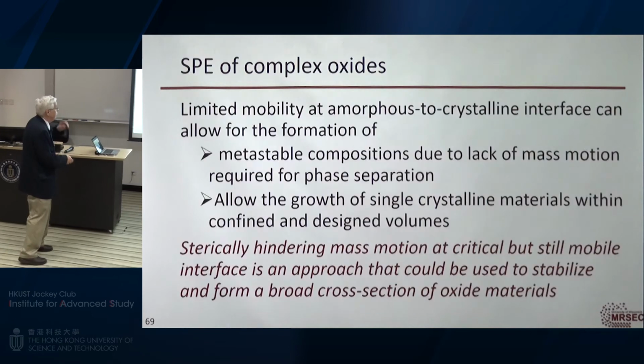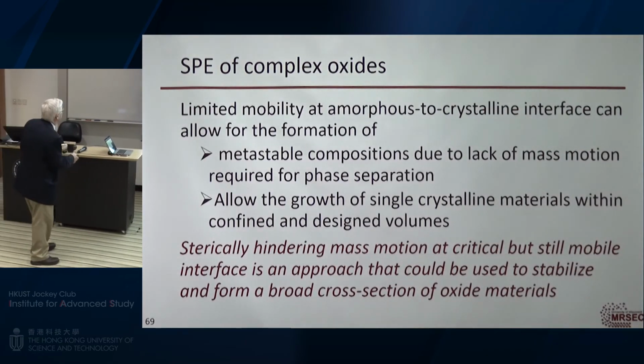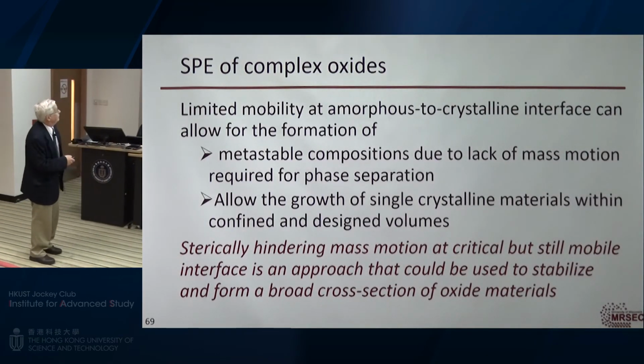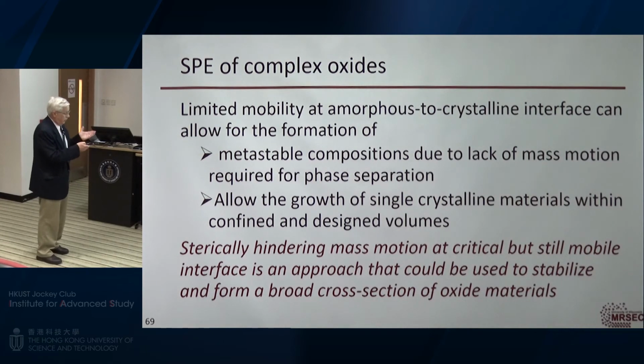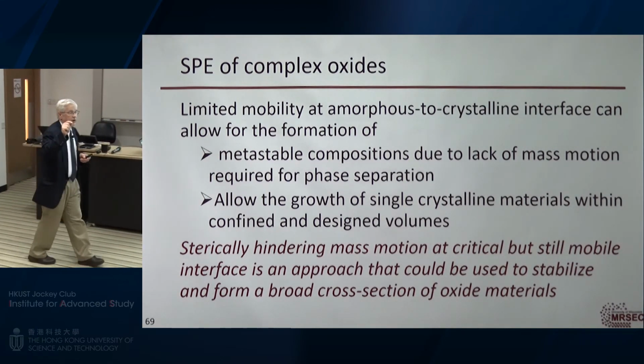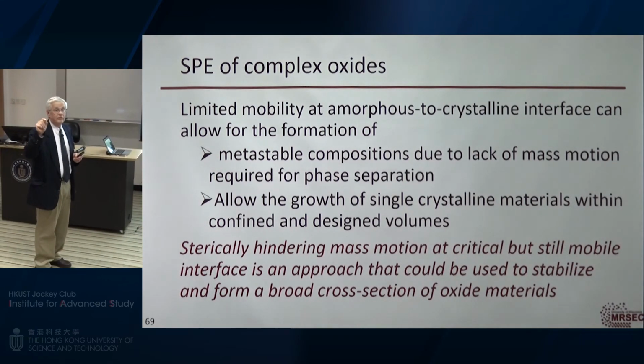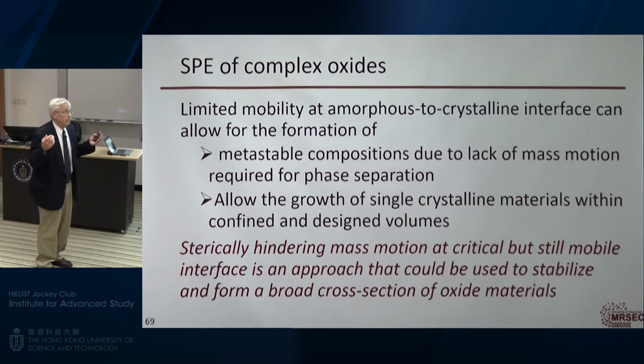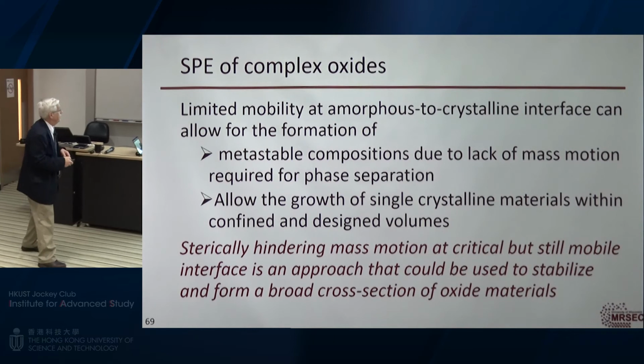So we'll move on, just in the interest of time here, and summarize that. I showed you two ways that we made metastable materials. One is by controlling the chemistry at the surface to keep atoms from moving around and phase separating. Once they form, if I stop them from transporting on the surface, they get incorporated in the film, and I can put in metastable compositions that way.